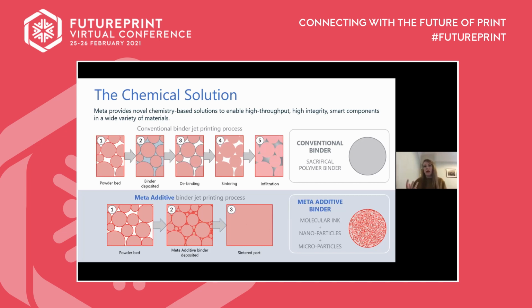But because you have to debind and then do a sintering step, you see large amounts of shrinkage rates. So you've also got to either predict how it's going to shrink, or you stick to straightforward, smaller, less complex geometries. And we also see sometimes for certain applications, we need this fifth step, which is an infiltration step, because there's some residual porosity left over in the component. And this ranges depending on the material you're using, but it can be as much as 20% porosity, which obviously isn't ideal, particularly when you're using them for applications such as automotive or aerospace. So you need this infiltration step.